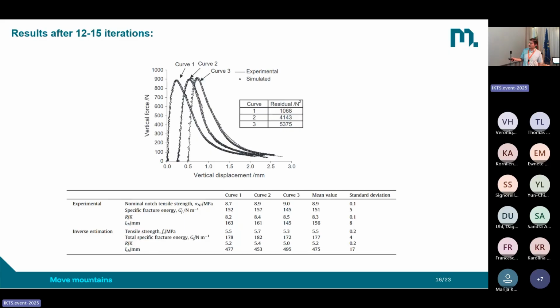And we are receiving here then this parameter set. Now I would like to discuss it a little bit. From the nominal notch tensile strength here, we got 8.7 megapascal. And for the tensile strength from the inverse evaluation, we're getting 5.5 megapascal. So you see it's a significant difference.